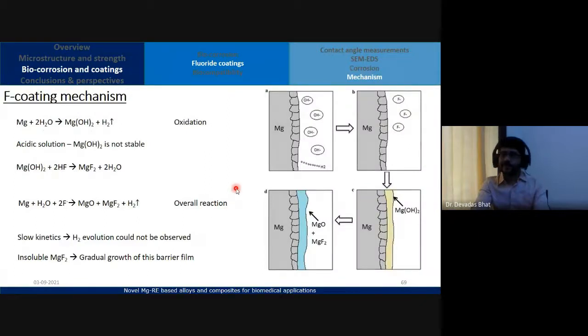This is the mechanism of the fluoride coating. So you have in the beginning the evolution of hydrogen, formation of hydroxide, and then when you introduce that into HF, hydrofluoric acid, you will have the stability of the hydroxide, because in the acidic solution the hydroxide is not stable, and you will then get MgO, MgF2, and that is the overall reaction.